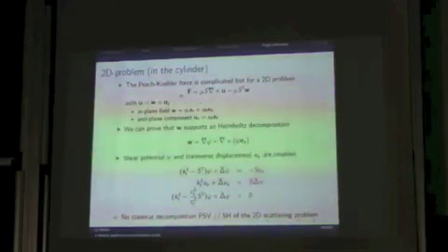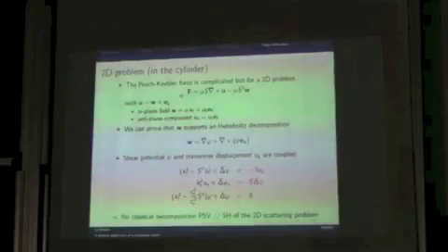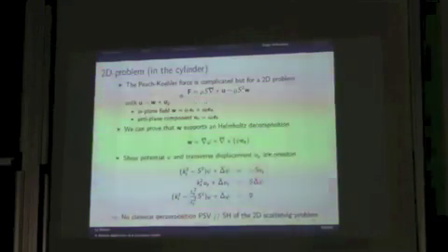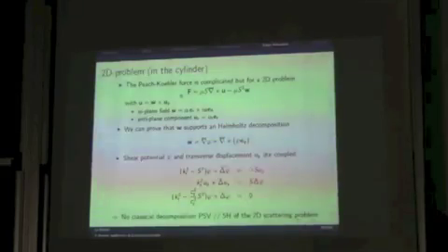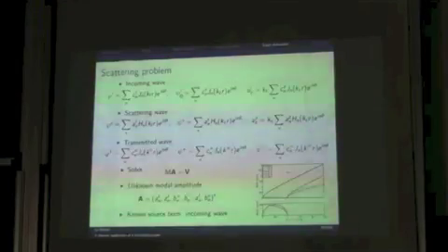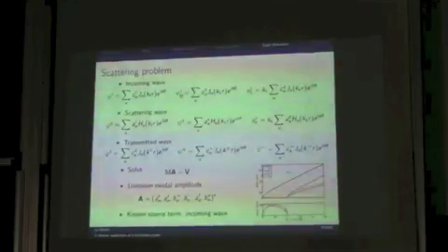If I send a longitudinal wave in this direction, in elasticity, I will observe a shear wave in the same plane, and a longitudinal wave in the same plane. Here, I will observe something else, which is a transverse shear wave. So, first we have to write down all the equations.